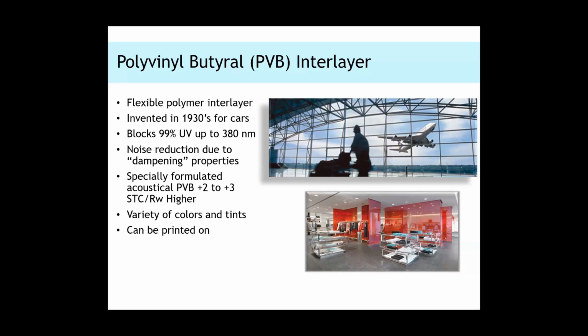And then noise reduction. The softer the PVB is, the more sound it will absorb from coming inside the car or inside the building. In general, just adding PVB to a glass window or door will improve the STC by about 2 decibels. We also have an acoustic PVB that improves the acoustics by 5 decibels in one piece of glass. The PVBs come in different colors and tints, and they can be printed.